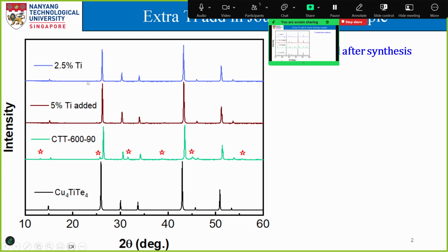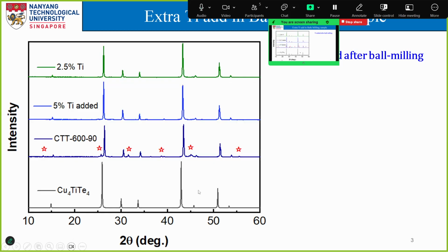I see. Amazing. Such a beautiful trick, the simplicity of it. Basically, I think the hypothesis was that you're doing it because there's excess copper telluride. That means that there must not be enough titanium to react, and we added more. Beautiful. Man, that's fantastic. This is really amazing.